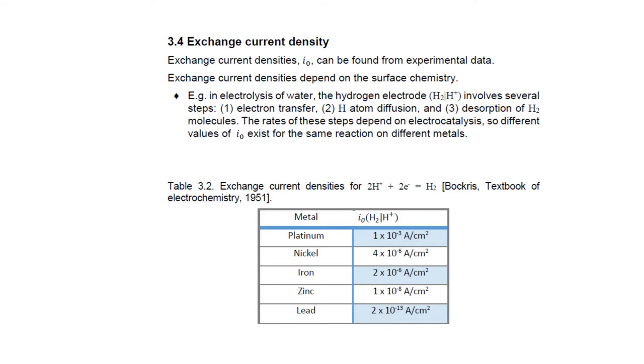At the same time, looking down the table, we see iron supports a reasonably high exchange current density for the hydrogen reaction of 2 microamps per centimeter squared. And this is consistent with the fact that we know iron, thermodynamically, we expect it to corrode in aqueous solution, and we also know that it corrodes fairly fast. That's consistent with the fact that it's quite a good catalyst for the hydrogen reaction. A bit further down the table, zinc, we also know actively corrodes in aqueous solution, but actually it corrodes slower than you might expect, partly because it has a slower exchange current density for the hydrogen process.